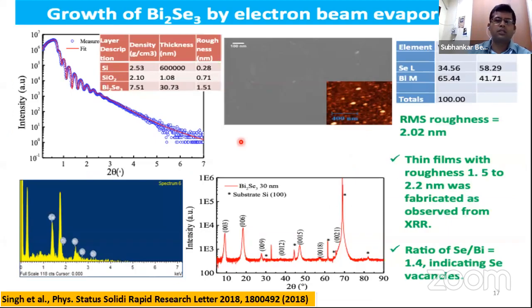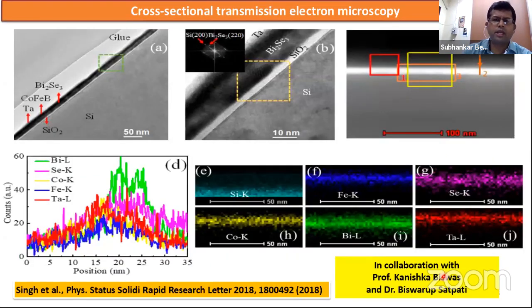However, our approach was a bit different. We tried to deposit the bismuth selenide by electron beam evaporation, and I think we were the first to achieve it successfully. The difference is if you do it by MBE, then you can achieve epitaxial bismuth selenide with nice quintuples. However, in our technique, we get polycrystalline films. But if you look at the planes, all the 003 planes are coming very nicely. And we found there's a little bit of selenium vacancy, but that's pretty much the same even in MBE prepared thin films.